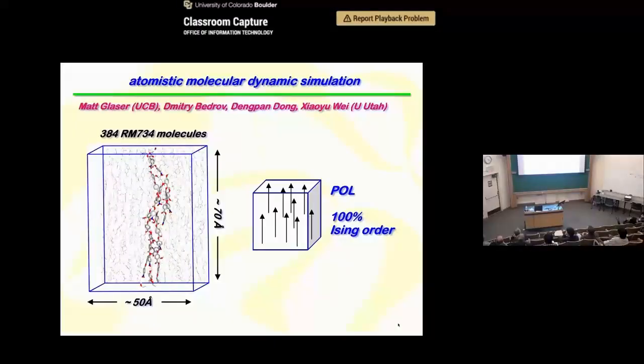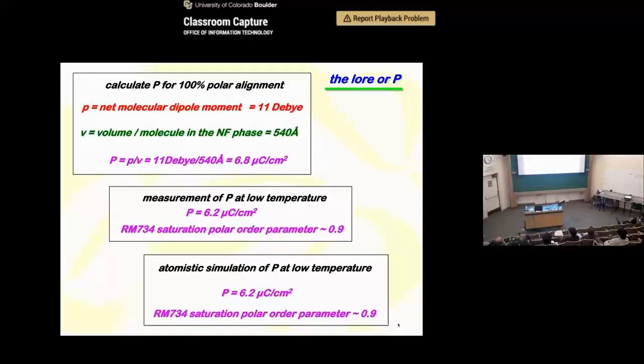We could calculate from the simulation the polarization in this condition when we have 100% Ising order. We don't have perfect order because the molecules are fluctuating around. So in the simulation we end up with a polarization of 6.2 microcoulombs per centimeter squared, the same as the experimental value. So we interpret this to mean that in the saturated ferroelectric nematic phase, we have near 100% Ising order.